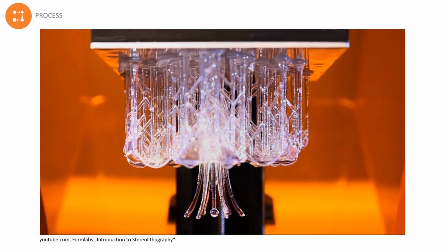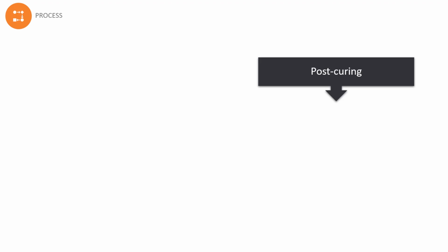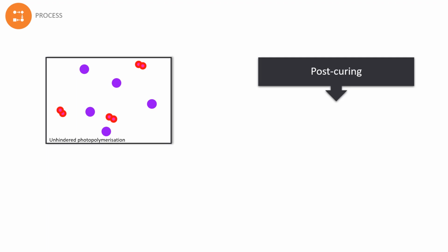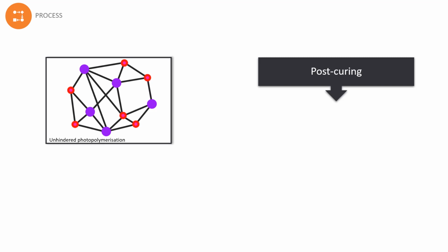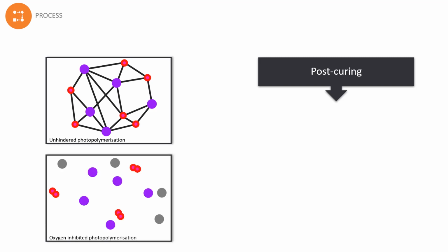The first thing to be done is the post-curing. This is necessary because the printing is not performed under vacuum. Therefore, oxygen is present in the building chamber, and oxygen is a polymerization inhibitor. In a completely unhindered curing process, the purple monomers together with the red photoinitiators form a nice and stable 3D network. In contrast to that, an inhibited process turns out differently. Under the presence of oxygen, represented here by the gray shapes, the network will not be as stable because the oxygen molecules react with the photoinitiators and stop the chain propagation. This means small portions of the resin are not completely cured after printing and need to be post-cured.